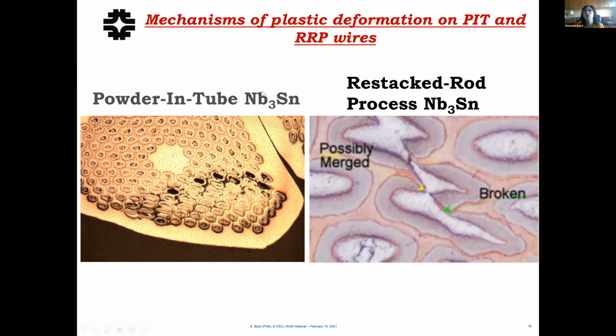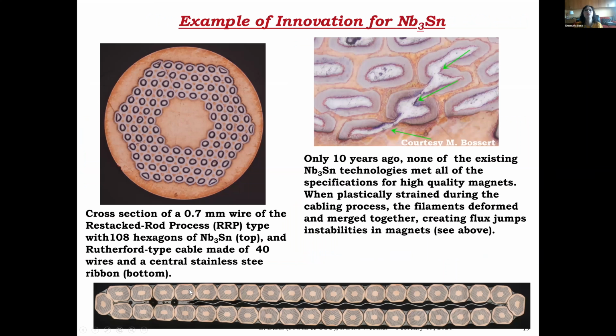Here I'm just showing a powder-in-tube type of niobium-3-tin. There are several types, but this one couldn't be used because it just broke under cabling. So you see, there were a number of different types of niobium-3-tin conductors, so you have to decide which one works in your cable. The powder-in-tube didn't work, so we went with the restack rod process. However, we had to fix this problem. So this is what I just said before. In these cables here, the deformation and the phenomena that happen are of this kind in this specific material.